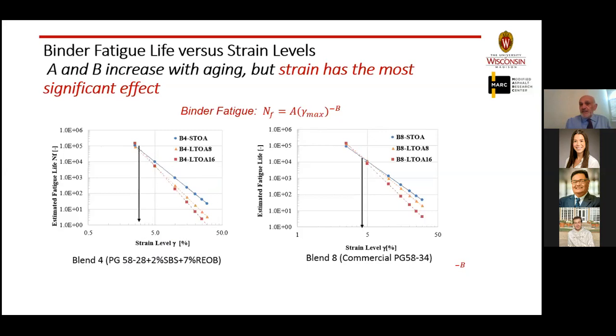What's also interesting is seeing the effect of the aging on the fatigue law. And what we found out is, you can see here, this is short-term oven aging of an asphalt mix. We took the binder, extracted and recovered from the mix, and tested it after 2+2 aging, 2+8, and 2+16 hours. And what you see is a very clear rotation of the curve in a very specific way. What is the way? It's actually clockwise rotation of the fatigue law.